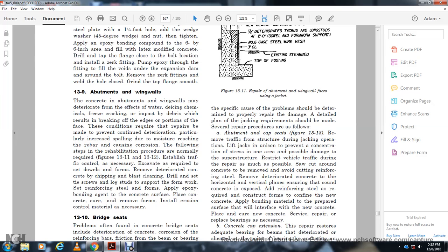13.9. Abutments and wing walls. The concrete on the abutments and wing walls may deteriorate from the effect of water with de-icing chemicals, freezing cracks, and the impact of debris, with the resulting breakup of the edge and portions of the face. Repair is required to prevent continued deterioration, particularly the exposure of rebar and corrosion.